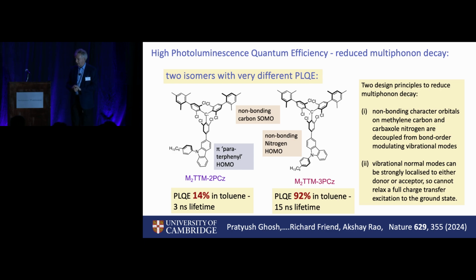But one of them has got a luminescence yield of 14% and a relative lifetime of 3 nanoseconds on the left. The other one, in toluene solution, has a luminescence yield of 92% and a much longer emission lifetime because there's less non-radiative competition. So why, by switching the point of connection on the carbazole to the TTM group, does it change?